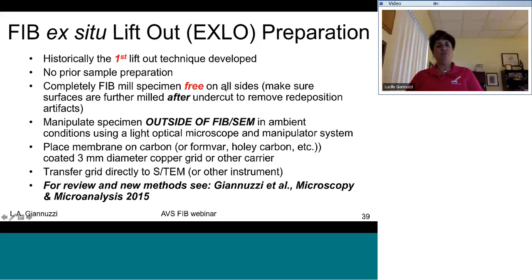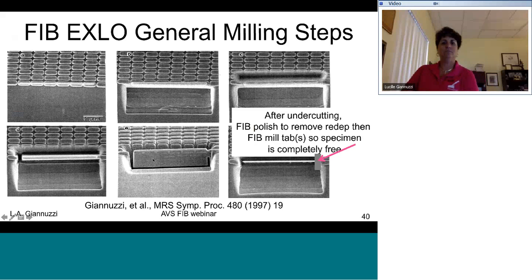Okay, so now ex situ lift out. I'm sort of going backwards in time because this was historically the first lift out technique developed. Again, all the advantages of in-situ lift out except for you're doing this outside of the FIB-SEM. There's no prior sample preparation. You completely FIB mill the specimen on all sides. You manipulate the specimen outside of the FIB. And if you're using this for TEM sample prep, you want to do also your final thinning inside of the trench, and then you cut the sample with tabs free. Then you can mount the sample onto a carbon-coated TEM grid or some other holders as well. And I'll show you various examples of this.